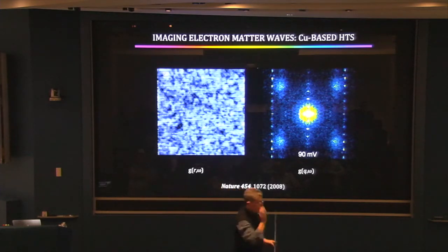One small question. Is this the best way we have of actually visualizing band diagrams today? So you can use photo emission to measure the band structure of compounds. The energy resolution of photo emission is a few milli-electron volts. Our energy resolution is between 100 and 1,000 times better. So if you need very high precision, this is the best way. If you need a kind of quick and dirty analysis, photo emission is the best way. Very good question.